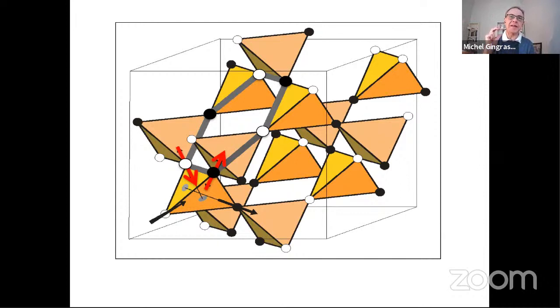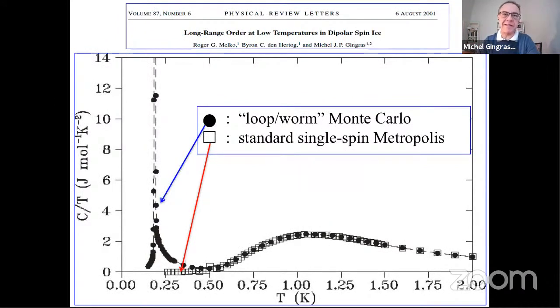I call it excitation because in the dipolar case, it's not a zero energy excitation. The small energy fluctuations between these configurations would be exactly degenerate for the nearest neighbor model, but they are not in the presence of the long-range dipole-dipole interaction. But by going from this low energy state and essentially bypassing the huge energy barrier that we would encounter by single spin flips, we can very effectively explore the low energy states. And of course, these loops don't have to be only hexagons as illustrated here, but they can span the whole system. There's some interesting statistics having to do with loops spanning the system and topological sectors, but I don't want to get into this in this talk.